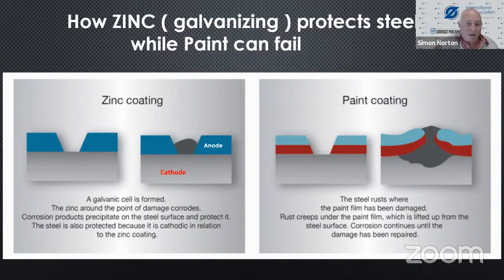But if you have paint and you have a nick in the paint or a scratch or damage, the atmosphere gets through to the steel, the corrosion products form, they lift the paint, go underneath the paint and destroy the protection of your steel. So the moral of the story is first galvanize, then coat. And Terry will talk about that as duplex coating.